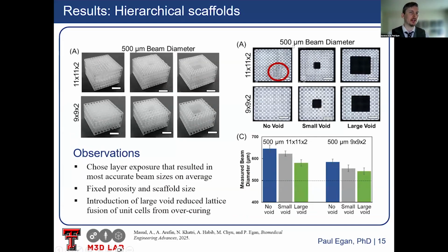And so our results, we created these hierarchical scaffolds. You can see the 500 micron beam diameter versions here. We tried it with no internal pore and then a large internal pore. And so what you're seeing here in the top right is when you try and print a lattice in DLP and resin printing, you can get this overfusion where the pores just kind of close off because there's too much material there. And so adding that hierarchical pore in the center, it allows you to avoid that over curing, so you get more of the beam diameter that you'd like in the system, but also it's good biologically because you get that large central area for that biological nutrient transport as well.